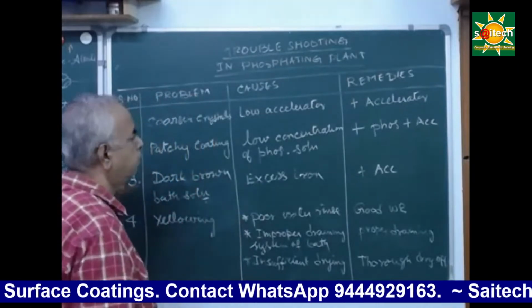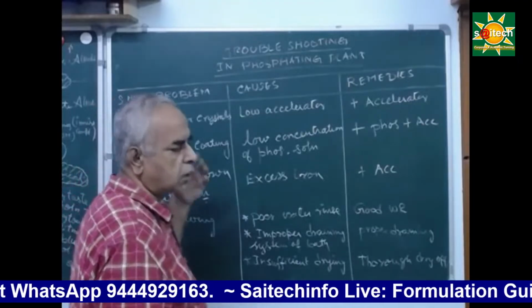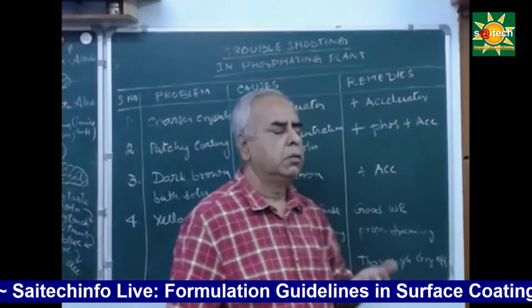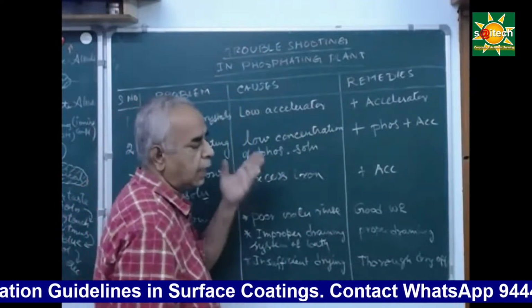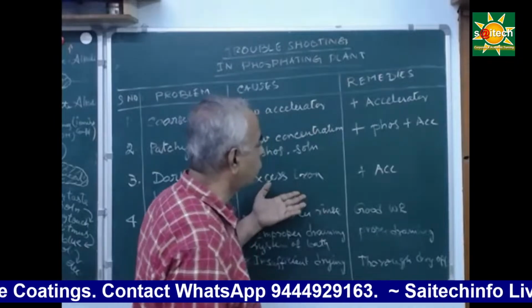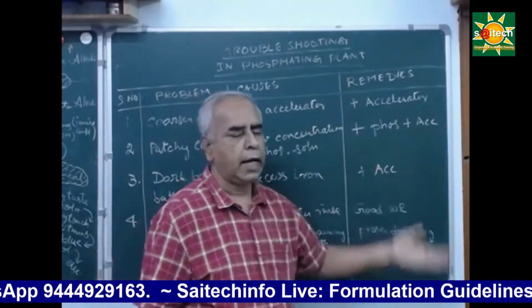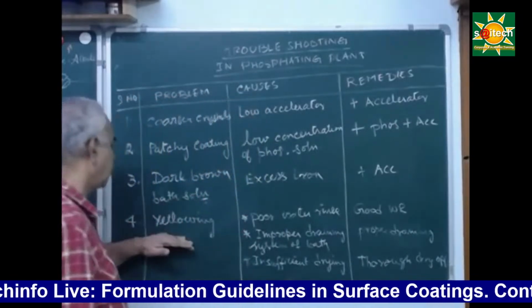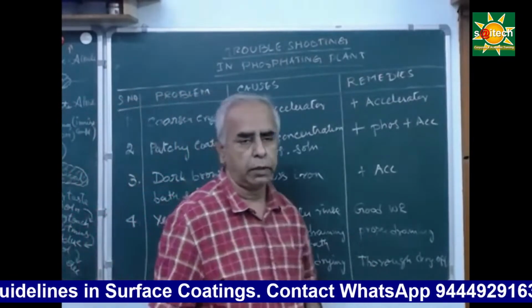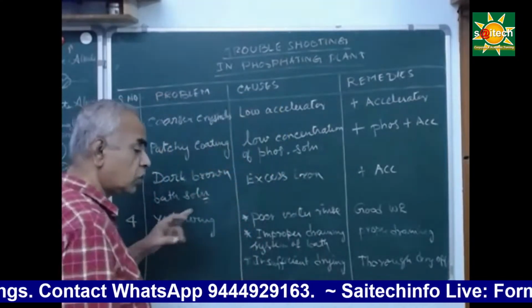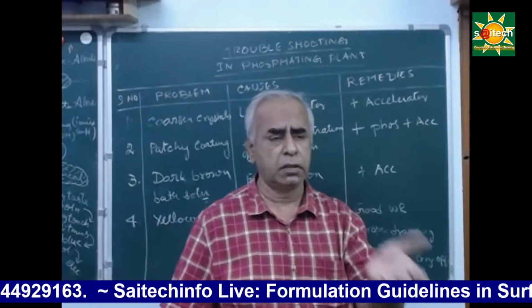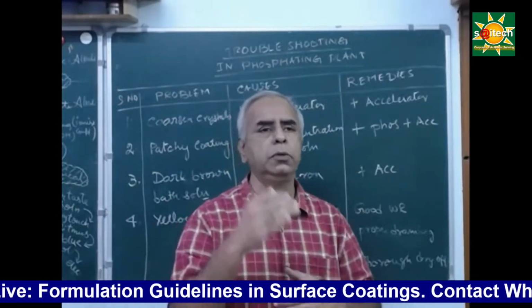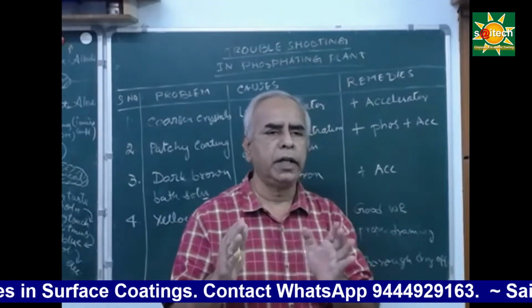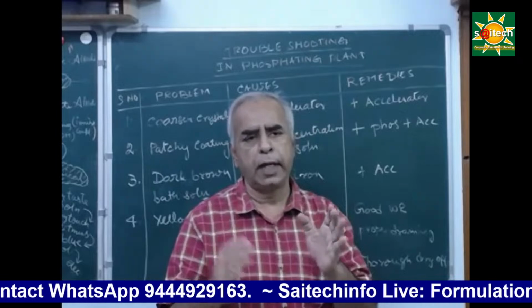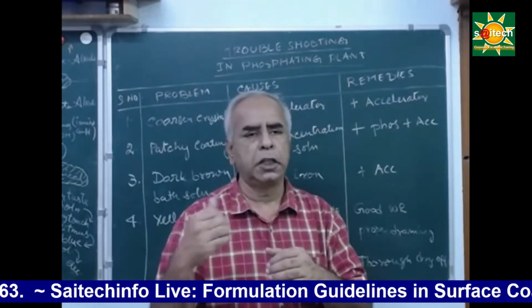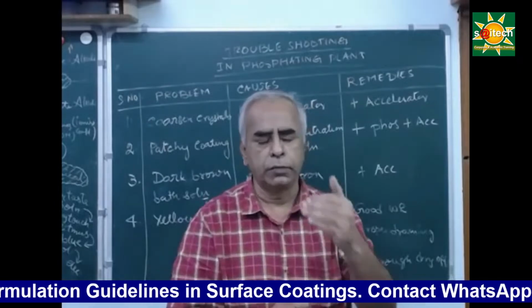Next, dark brown bath solution. Sir, my solution has become very dark. Okay, so it is due to excess iron. So this excess iron should be driven away, and you can add accelerator also. Otherwise you have to replace the bath. That is the best way. Okay, then if the bath is very old, sometimes such a type of problem will arise. So how long you can maintain the bath should be carefully planned, and that is obtained in consultation with your phosphate coating chemical supplier.